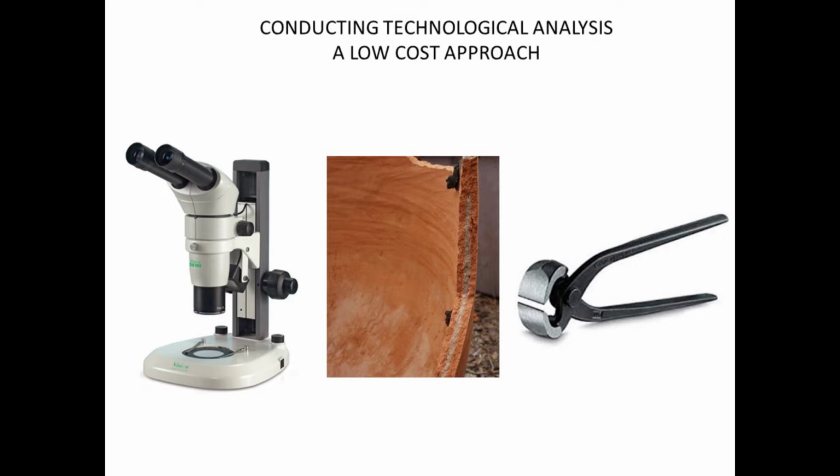Technological analysis implies a combined analysis of surface features and microfabrics, examining in particular fresh radial sections, sampled at around mid-height of the vessels, not in the base or rim areas, with the stereo microscope at 10-30 magnification. This practice is apparently not yet common, either because archaeologists have a negative view of breaking sherds, or, I presume, because it's considered difficult to examine the sections and more precisely to detect the attributes: significance of coil fissures, coil size, coil placement, as well as to analyze the orientation of voids and inclusions to evaluate how rotary kinetic energy was used. This examination of radial sections is absolutely necessary to accurately describe forming techniques.